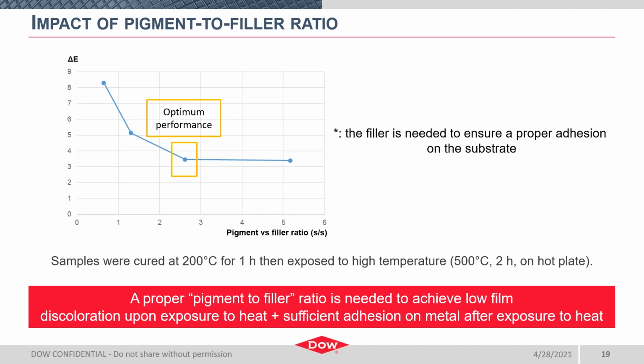In addition to PVC and pigment to binder variations, we also looked at pigment to other functional filler ratio, in this case, silica, as we know that this will also impact coating performance, specifically after exposure to heat. This graph depicts how pigment to silica ratio impacts the color retention of a coating after exposure to 500C, y-axis being delta E, or color change, and x-axis is that pigment to silica ratio increasing from left to right.